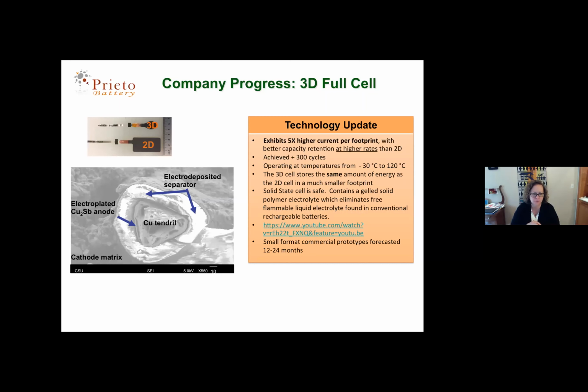The SEM image on the bottom left is a cross-sectional image of part of the foam. You can see the copper tendril in the middle, the really thin copper antimonide anode, the electrodeposited polymer electrolyte, which is charging a little bit under the electron beam, and then the cathode slurry. So the 3D structure can handle about 5 times higher current per footprint than the 2D battery can, with much better capacity retention. And I'm going to show you a plot of that. Under controlled depth of discharge, we can achieve about 300 cycles. So a big effort right now is improving our cycle life.